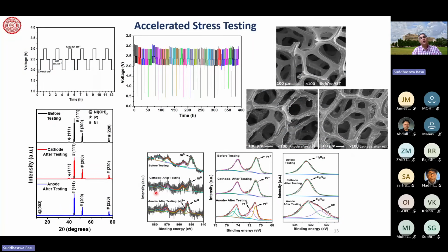And this is kind of a side view. You can see small hydrogen bubbles here and there at different velocities, right? And then we did the accelerated testing, where we went through a voltage fluctuation. And if you do the voltage fluctuation, you can see it goes back to the original voltage. We did this through the accelerated test protocol that is available at the DOE site.